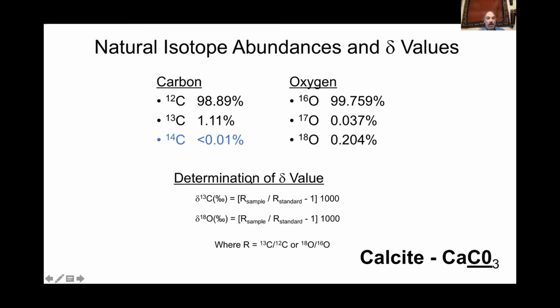And if you're of a quantitative type of person, we take those ratios and we throw them in this calculation. I don't want to go into it, but essentially what we are doing is measuring the ratio of the 2 most common stable isotopes, carbon-13 and carbon-12, oxygen-16 and oxygen-18. Okay, and again, they are coming from the mineral calcite. So this is the calcium carbonate. So this is the mineral that makes up marble. And it's the carbon and it's the oxygen that we're interested in, and we're measuring the isotopes.